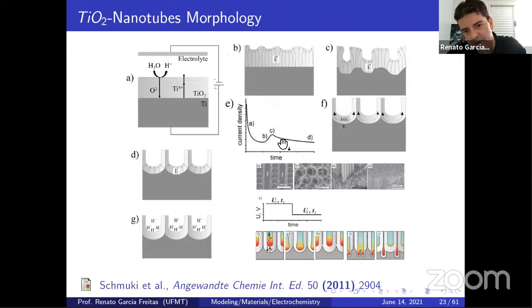And we have a decrease of the current constantly as soon as we increase the titanium oxide nanotube layer thickness. And we have for sure the water splitting here and a gradient of voltage. The larger the potential used to obtain the nanotube, the larger the tube. As soon as we decrease to a small voltage, the tube becomes small. With large anodization values, we have the thicker nanotube. So we can obtain titanium oxide nanotubes from a few nanometers up to micrometers. And we have the gradient of this one.